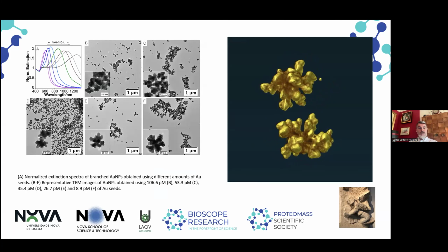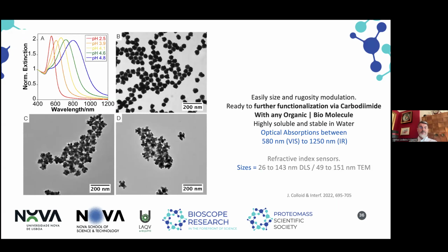And we are now in collaboration with the University of Angers in France to try to use these inorganic nanoparticles to entrap some organic molecules that can be used later for sensing or for imaging. So this particle has the positive property that it can be functionalized via carbodiimide. So any organic molecule that can react via carbodiimide reaction can be functionalized with these nanostars. They are very soluble in water, and we can modulate the plasmonic band from 580 nanometers, for the pure spherical one, to 1250 nanometers for the blue one, which we made mainly at pH 5.